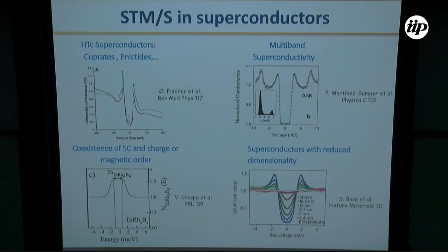Well, there are many materials where multi-gap structure has been observed. Maybe the most prototypical is the result in MgB2, where two clear peaks appear in the tunneling conductance due to the two-gap structure of this material.